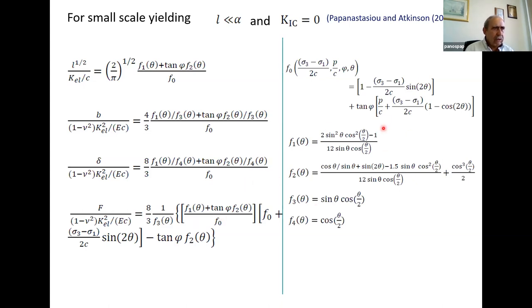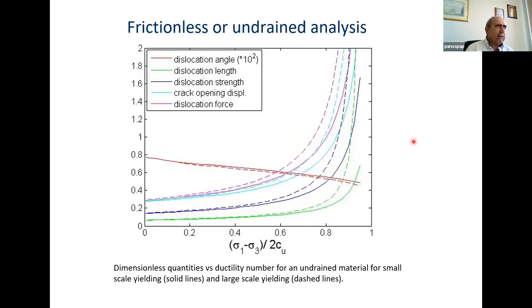And with this function, we can identify some critical parameters, which you will see more clearly in the results I will show next. So the first critical parameter is the parameter you see here in the horizontal axis: the difference between the stress along the fracture propagation minus the closure stress, divided by the undrained cohesion of the material.